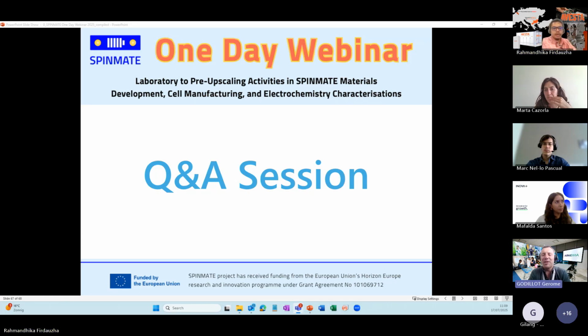Sorry, just one comment, maybe on the environment. It is important for the cathode, but it's very important for the membrane, because in the end in the pouch cell it will be in contact with lithium metal. So you cannot have water in your membrane. Everything was done at lab scale in the glove box, and at pilot scale in a dry room. Even the mixing and coating step was done there for the membrane, because it's very critical, as it's in direct contact with lithium metal. For the temperature, maybe not really a problem, but for the atmosphere, yes, between the argon glove box and the dry room, which has a dew point quite below -50.